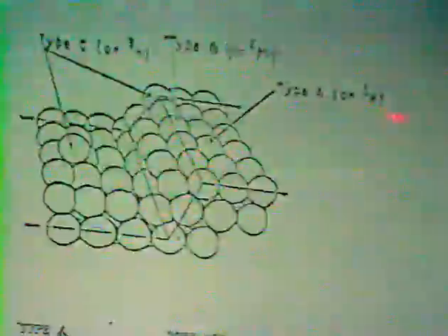Now, to get everybody in the same line of thinking, and this is probably going to be kind of old stuff for most of you, metal particles seem to have essentially three different kinds of sites on them. Some of them can be divided into other subcategories, but basically we have corner sites, which Siegel has called 3M sites, and others have called a type C type site. Add atoms also fit in that category. Edge sites, which Siegel has called 2M sites, and planes or terraces, if they're on a sliced metal, which are called 1M sites.